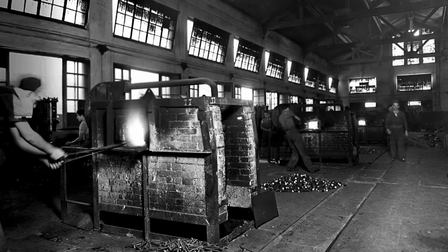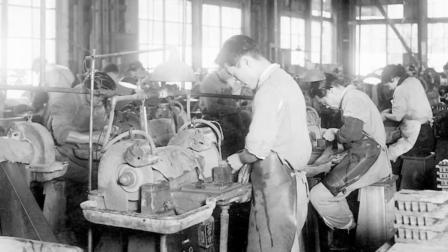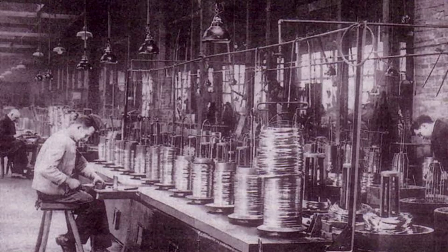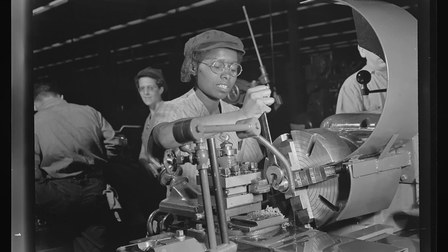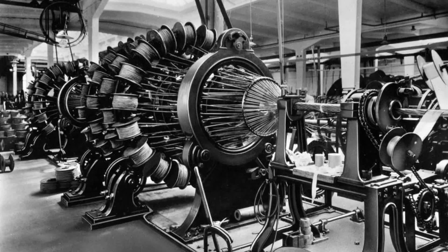In 1930, the manufacturing process improved. A better way of sawing carbide helped reduce production time. Powder molding methods expanded the shapes that could be produced. Wire drawing dies began demonstrating the kind of wear resistance that had originally attracted engineers to carbide. One mill using carbide dies reportedly reduced scrap dramatically. Slowly, the failures produced rules. Carbide needed support. Carbide needed rigidity. Carbide needed controlled geometry. Carbide could cut much faster than steel, but only when the rest of the system was built to take advantage of that speed.